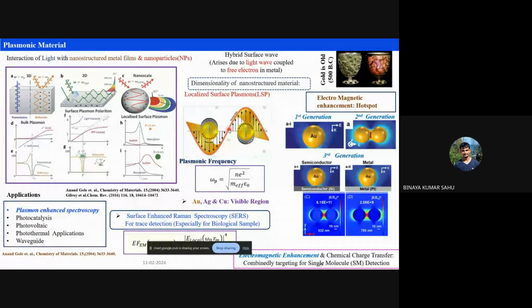Or what I want to tell, if you want to enhance the Raman spectra of tin oxide, what you need to do is keep some gold nanoparticles and keep your material close by. Like here, I can keep my tin oxide near to this plasmonic material, and then I will take the Raman spectra, so that the Raman spectra of my material will be enhanced.